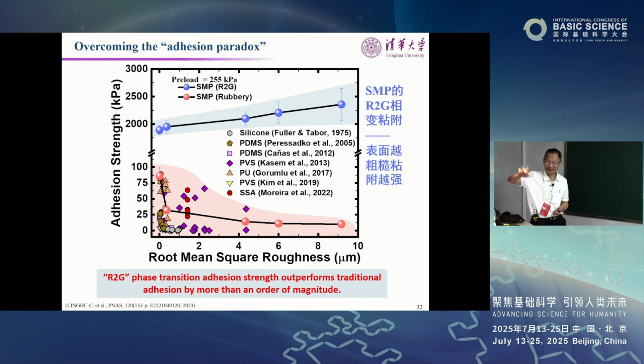You have more contact, more interaction. Second of all, the absolute magnitude of the strength has increased by one or two orders of magnitude. See here, this is a logarithmic scale. Increased by a lot, substantially increased. So the phase transition adhesion outperforms traditional adhesion by more than an order of magnitude.